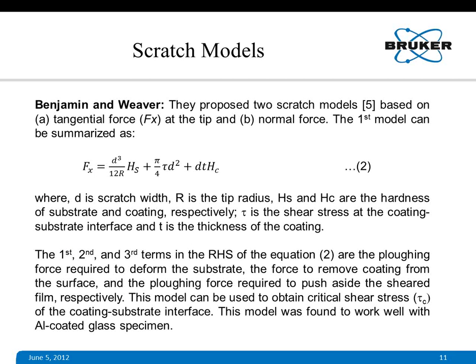Now we'll go through some of these scratch models which are available in the open literature. Benjamin and Weaver proposed two models, based on tangential force measurements at the tip, which is Fx, sometimes called friction force, and also based on normal force. The first model, as shown in equation 2, expresses the tangential force Fx in terms of hardness of the coating and the substrate, Hs and Hc. Hs is the hardness of the substrate and Hc is the hardness of the coating. D is the scratch width, small t is the thickness of the coating, and R is the radius of the tip, that is the stylus.